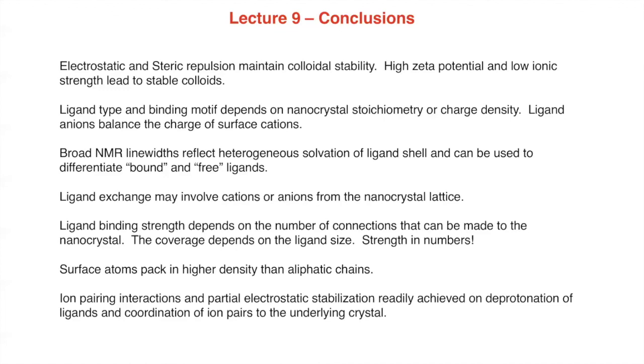A very important principle is that surface atom packing is more dense than the packing of straight aliphatic chains. And so you can't put an organic ligand on every surface atom. That's true on just about every material out there that I'm aware of. Even in cases where you have self-assembled monolayers on gold and chains are packed with near crystalline order, the density is lower than the density of gold atoms on that surface.